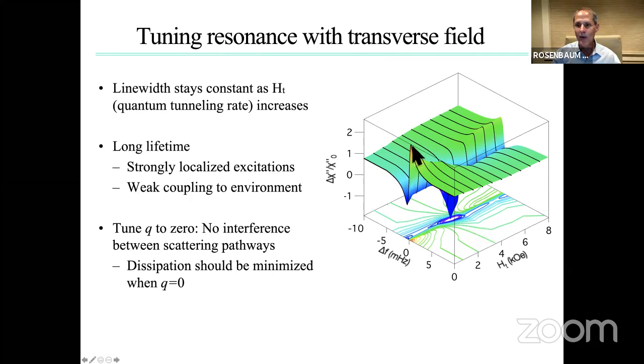You can see this is now a summary of all that data as a function of transverse field, where you're moving from one side of 0 to the other, and you can see the sharpness of this response. So there's weak coupling to the environment because of this large quality factor. And there's no interference then as Q goes to 0. So if there's no interference, the prediction is that there should be no dissipation. Now remember, we're measuring the imaginary part of the susceptibility, which is a measurement of the dissipation.